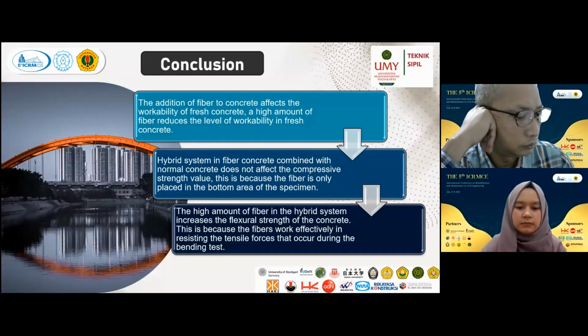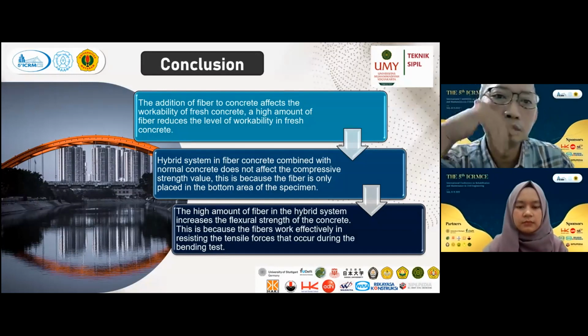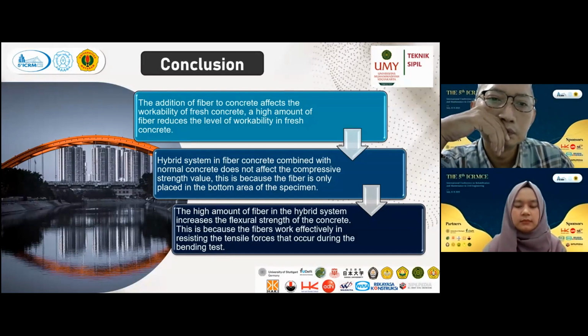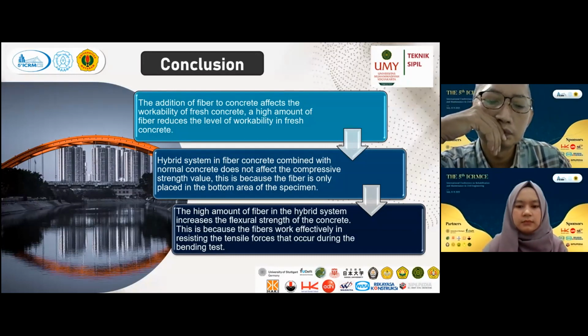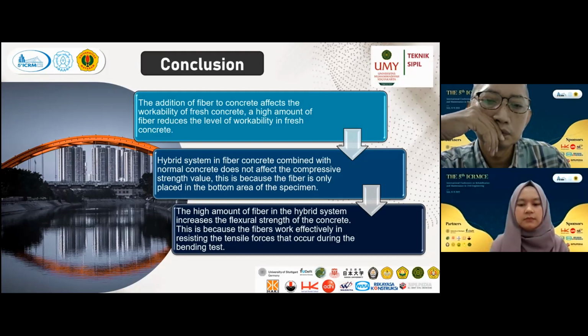And this is the conclusion from our research. The addition of fiber to concrete affects the workability of fresh concrete. A high amount of fiber reduces the level of workability in fresh concrete. Hybrid system in fiber concrete combined with normal concrete does not affect the compressive strength value. This is because the fiber is only placed in the bottom area of the specimen. And the high amount of fiber in the hybrid system increases the flexural strength of the concrete. This is because the fibers work effectively in resisting the tensile forces that occur during the bending test.